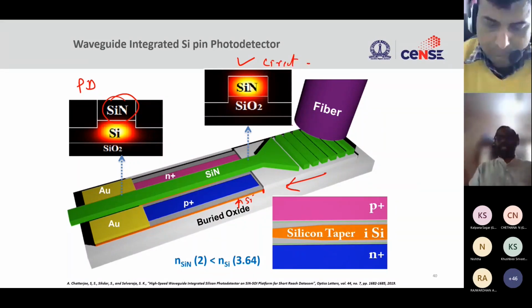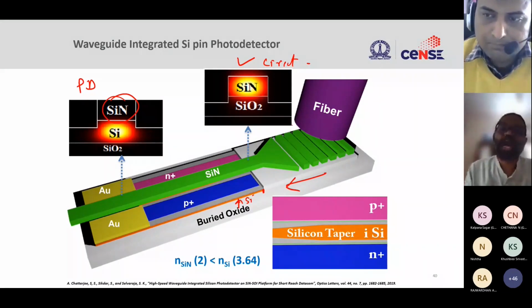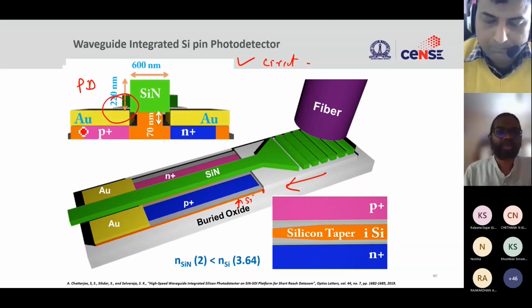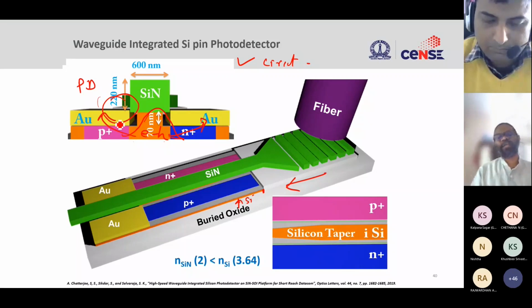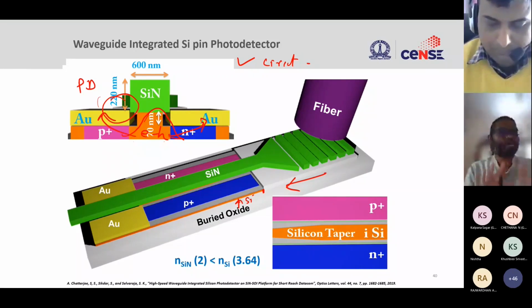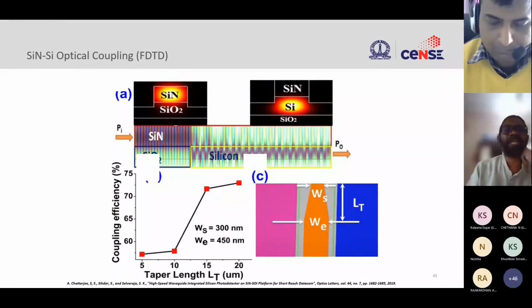And the photodetector is made in a very simple way. We have a PIN diode. All of you who have gone through basic semiconductors know that in PIN diodes, if you shine light in the intrinsic region, it generates electron-hole pairs, and you can take the electron-hole pairs out of the system, and it will create a photocurrent. And this is the cross section of that photodetector. The light is getting absorbed here, the electron-hole pairs are generated, and you can take the current out. As simple as that. PIN diode on silicon, and then we have silicon nitride as a waveguide. We did a lot of simulation work here as well, to understand what should be the length of the photodetector and how we could get better efficiency. You can see here a coupling efficiency in excess of 70-75% is possible using this.